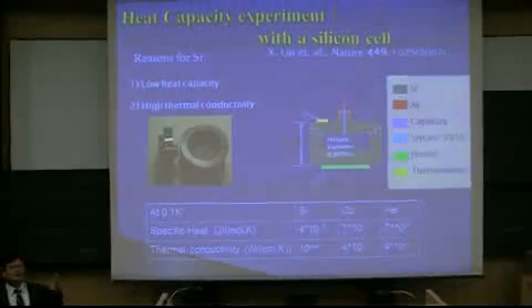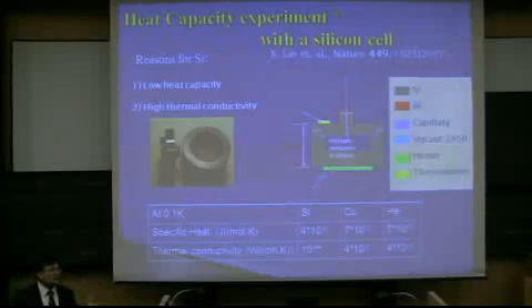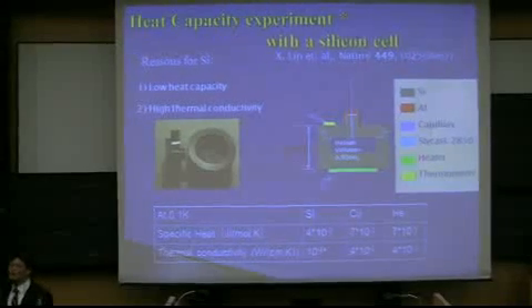So what they have done is they introduced single crystal silicon. It's 5-9 grade single crystal silicon, machined to make the heat capacity cell. It has a really low heat capacity since it is also an insulating solid, and high thermal conductivity. So they can measure the heat capacity of solid helium, and the background heat capacity contribution is only 10%